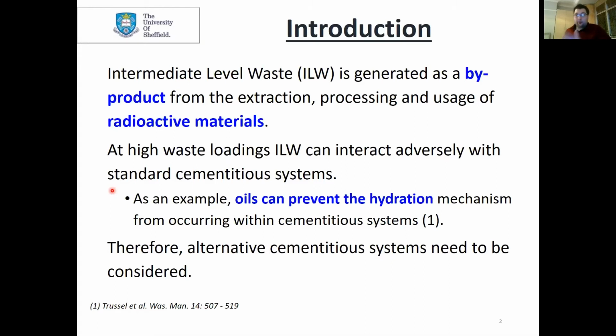It coats the cement particles and prevents the water from interacting with the cement by forming a hydrophobic layer. That hydrophobic layer stops the water getting in, and you get a very minimal reaction. So we need to look at alternative cementitious systems.